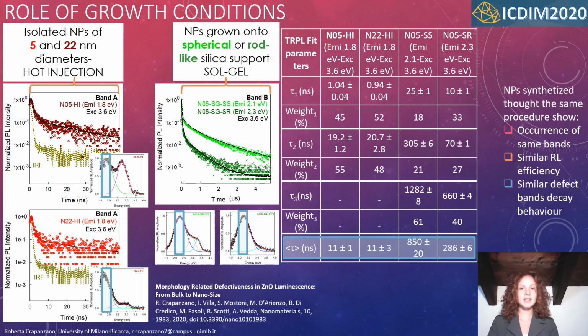This difference can be due to the different morphologies of the silica substrate, that in one case is spherical, while in the other is rod-like. Possibly, the morphology of the substrate influences the surface properties of zinc oxide nanoparticles, leading to a different defectiveness and hence to slight differences in the optical properties.